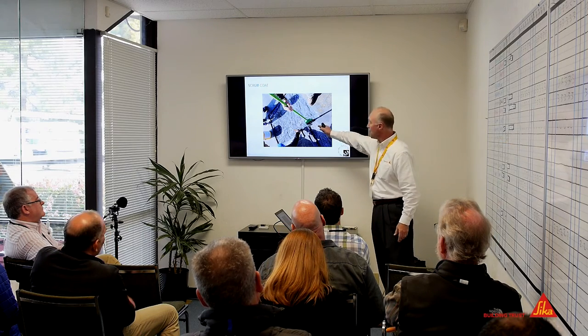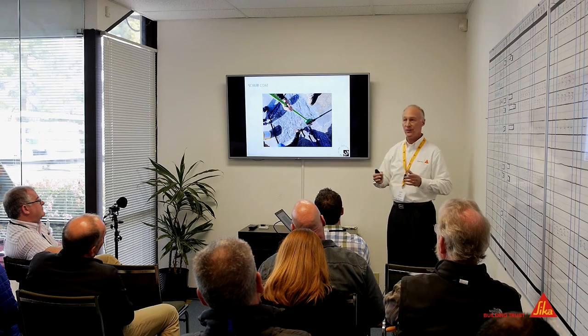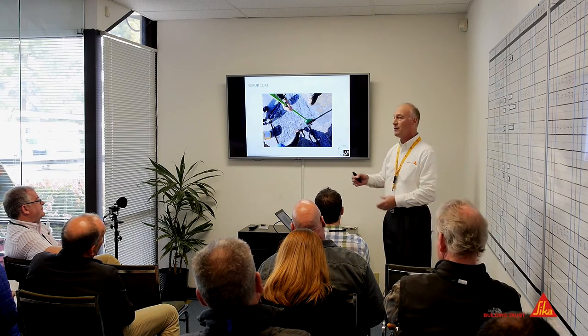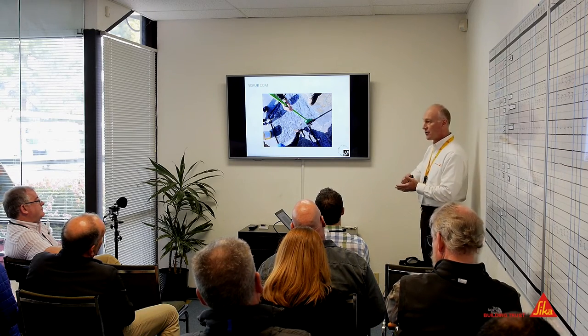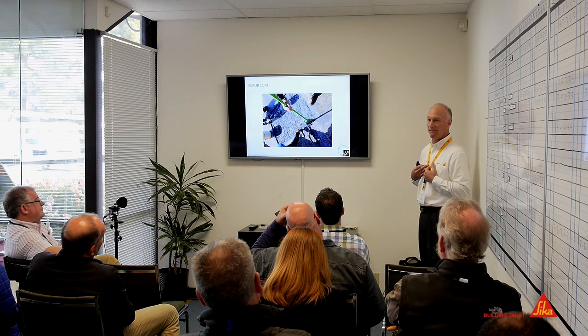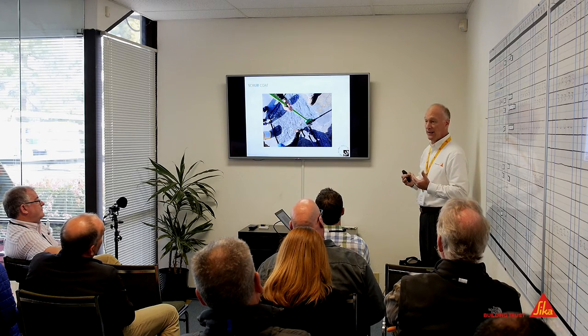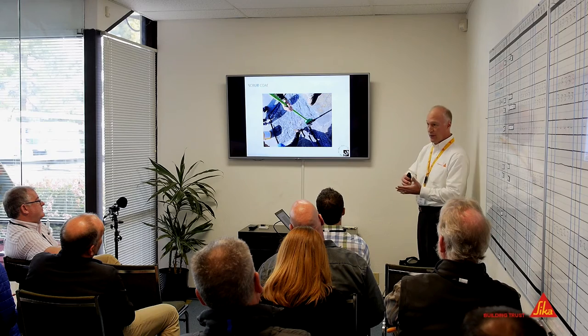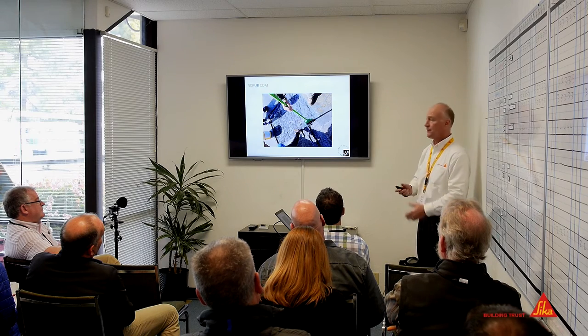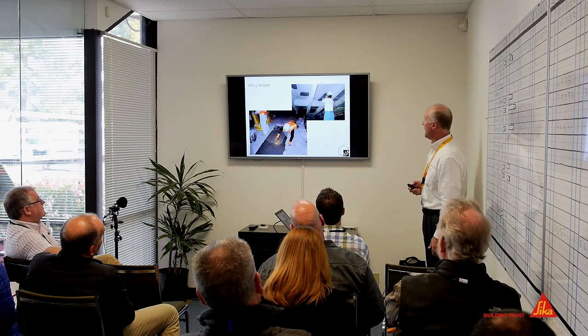Now the scrub coat can be either a separate material, a bonding agent, or it could actually be the repair material that you take and scrub into the substrate. For me, I don't mind either way. What you're trying to achieve is good intimate contact with the substrate. And then replacement of the spall material.